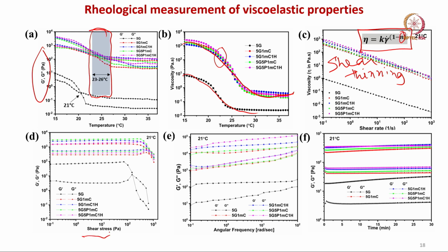So, both the shear stress and the angular frequency sweep of G prime and G double prime have been shown at the 3D extrusion printing temperature here, for the different composition scaffolds that we have made. When G prime and G double prime have been plotted with time, let us say up to 30 minutes, half an hour, we wanted to see whether this particular hydrogel remains stable at 21 degrees Celsius in terms of its physical properties, particularly storage modulus and loss modulus.